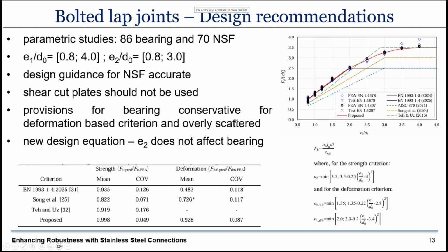We found that the provisions for bearing resistance given in Eurocode are overly conservative, and we proposed a new design guidance, a new design curve, a new design equation that is shown by this red curve, which better fits the experimental and the numerical results. In the new equation we propose, there is only dependency of the bearing coefficient on the end distance e1 and not on the edge distance.